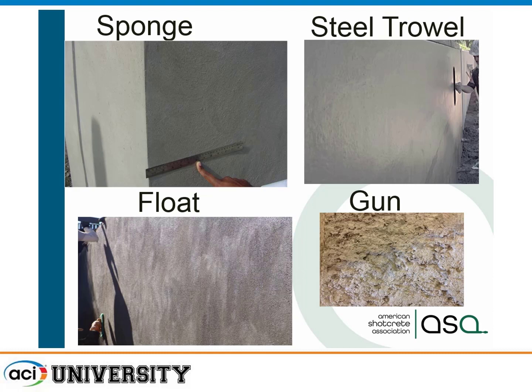We don't like the steel trowel finish just because how do you get the gloss from the steel trowel finish? You pull water up to the surface, right? So higher water cement ratio means less strength, so it will not perform as well durability-wise. The other thing is that it's a glossy surface. If it cracks, a little bit of cracking is going to show more. So we can do it. We don't like it. This is probably the most common finish, a float finish or a sponge finish.